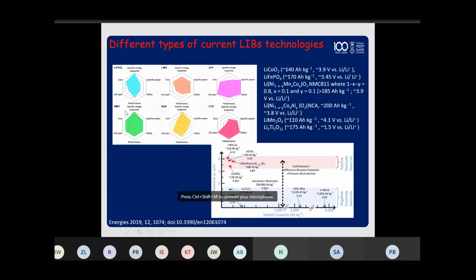Now, of course, the problem is a problem of sustainability. Cobalt is highly expensive and it's very difficult to mine, etc. Therefore, the next generation materials for electric vehicles are all based on NMC 811, where the ratio between nickel, manganese, and cobalt is 8 to 1 to 1, which means that we have highly increased the amount of nickel and decreased the amount of cobalt.